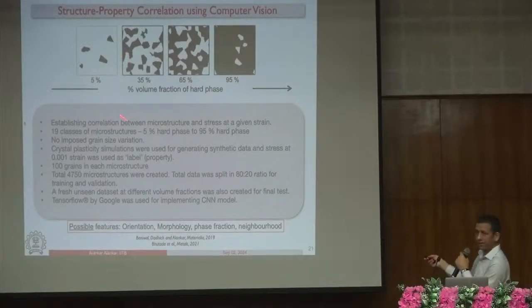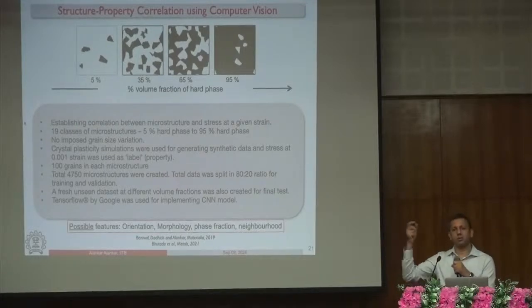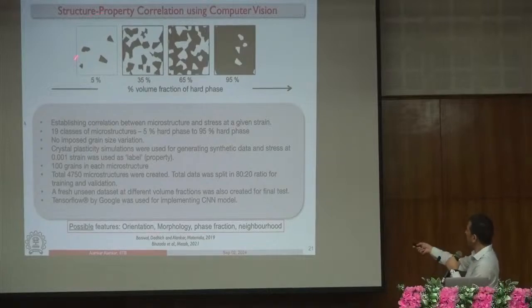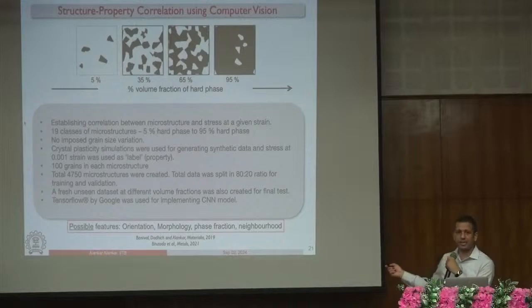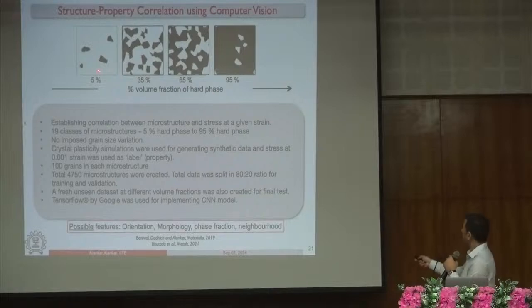For example, this is a multi-phase material which is all synthetic, by the way, and this was one of our earliest exercises because we did not have any data. Now, some of the industry partners have come forward and have contributed with similar data. In this case, we have a synthetic structure where we have a low elasticity modulus white phase and high elasticity modulus black phase, and the amount of black is increasing. That means overall this material has higher modulus of elasticity if you apply the simple rule of mixture, right?